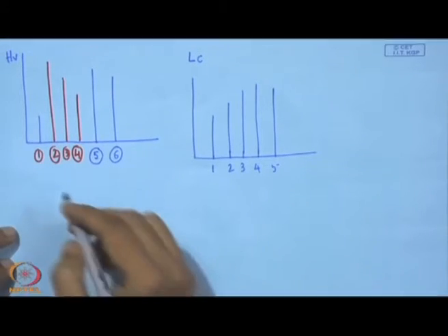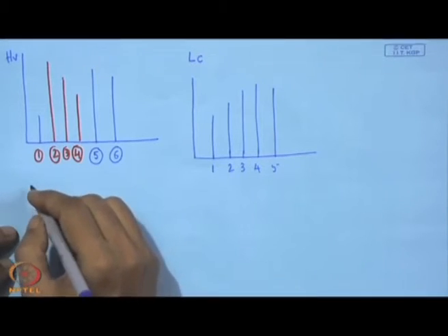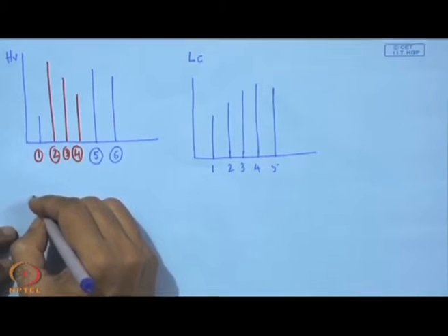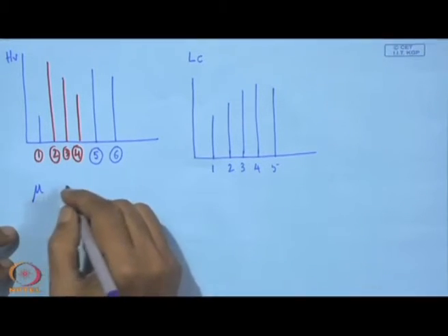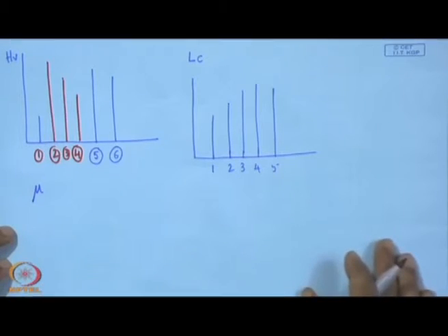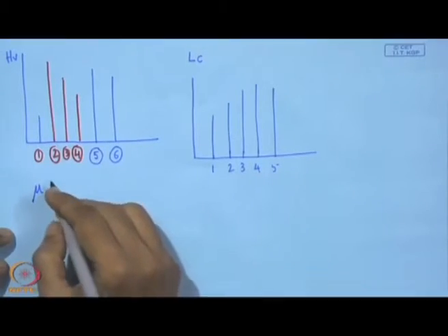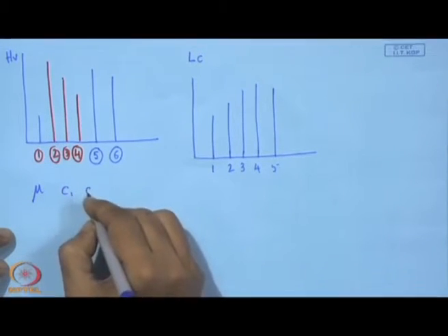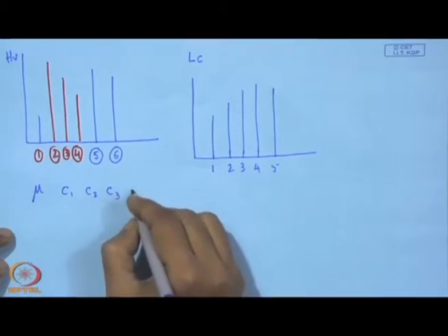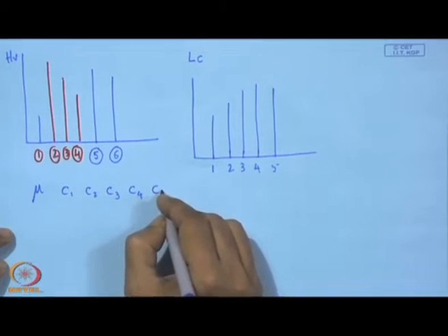Now, what is important is the coefficient of friction. This is the coefficient of friction one can find out in the ball on disc test, that means with a tribometer, with the pin on disc, and this is also our observation for these samples, C1, C2, C3, C4 and C5.